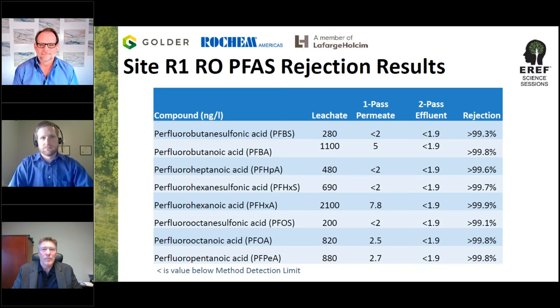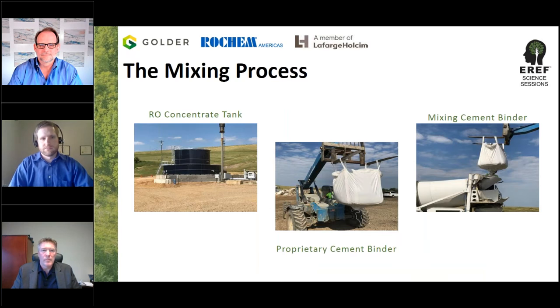Solidification is just what it sounds like. You're making something hard. In my experience, I have had dirt, sludge, slime, crud, slop, liquids, and you take these cementitious, pozzolanic products and you simply make them harder. The binders will start to bind in three dimensions, and as it does that, it will physically encapsulate those things which are not being destroyed. The heavy metals that have been converted to metal hydroxides are encapsulated. Any organics that are present are encapsulated. Within the confines of this webinar, the PFAS are simply large organic molecules that are fairly easily encapsulated as the binder starts to bind in three dimensions.